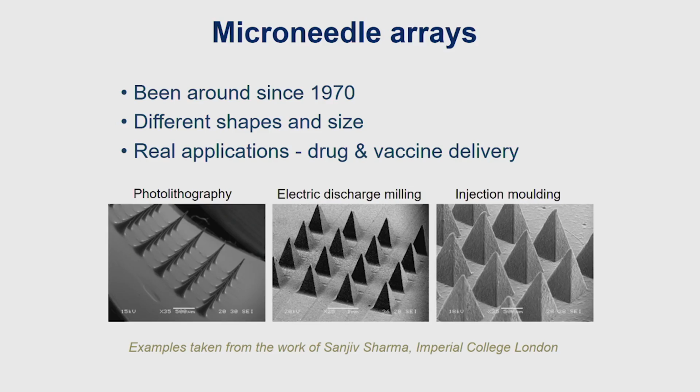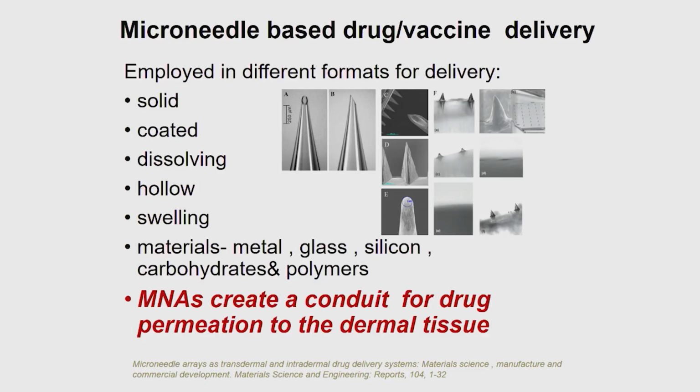Injection molding is a fantastic technology. It is a highly scalable technology. Now we make our biosensors, we make our microneedle platforms out of injection molding. And the nice thing here is you can make polycarbonate devices at a price of 10 pence, and you can make thousands of these injection molded devices. That's how cost effective and how scalable this technology is. And these are examples of work taken from my own work from Imperial College.